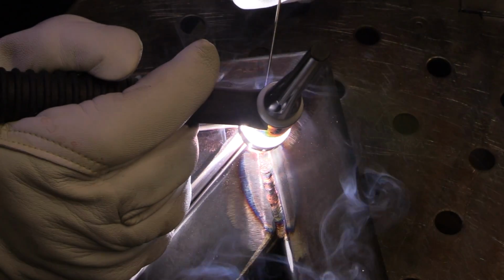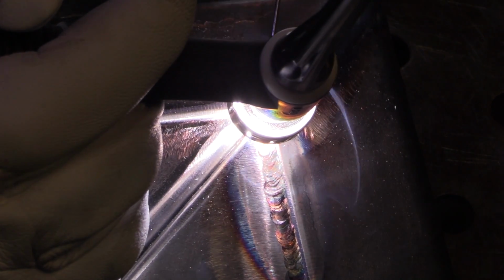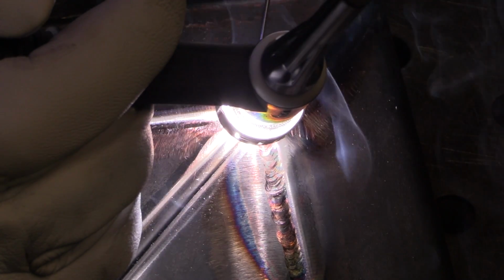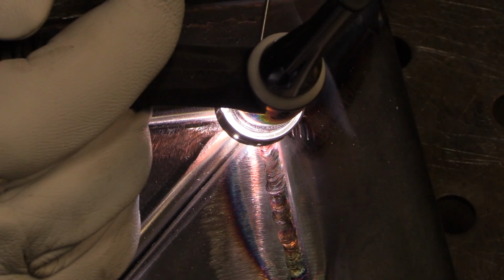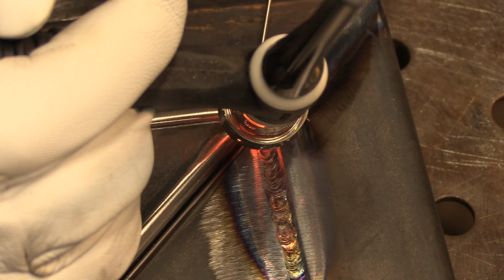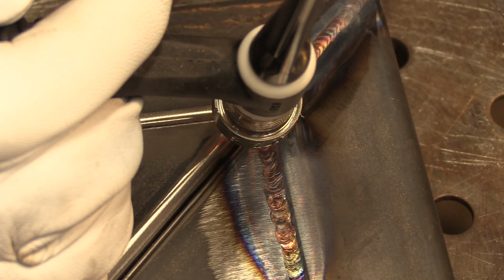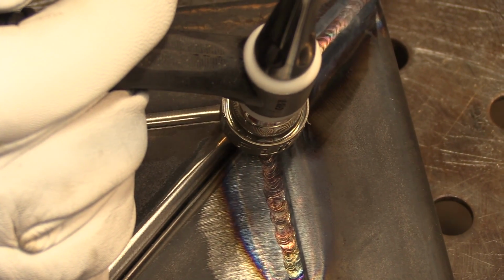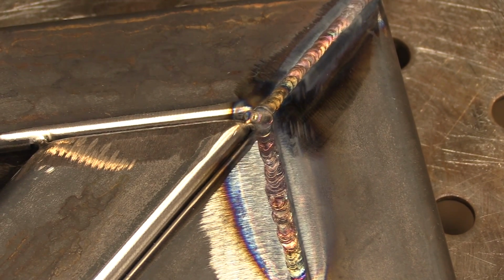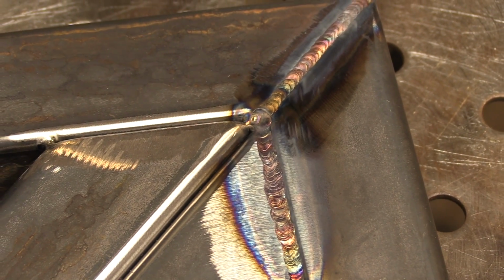So this one got a little squirrely on me, and you can see my torch angle is pretty much 90 degrees. I'm only leaned back maybe 5 degrees, and that, along with me using a little bit too much amperage, caused me to get some penetration and pull in some oxide from the backside. And that's what makes the bead kind of swim around like that. So it's a little bit irregular. Didn't go as well as the first one.